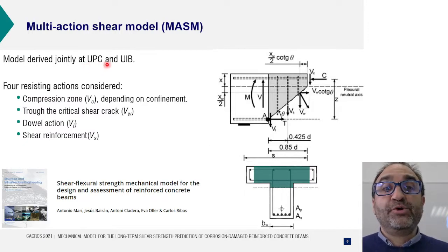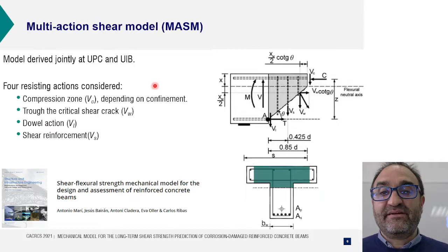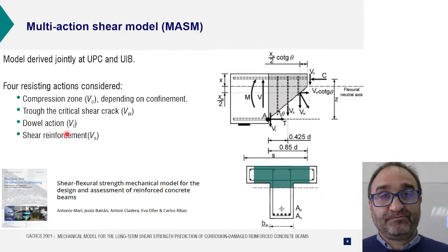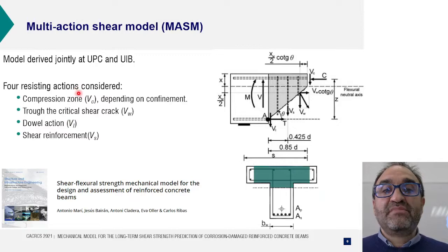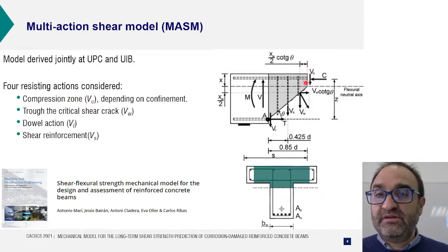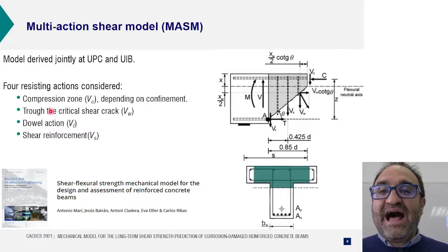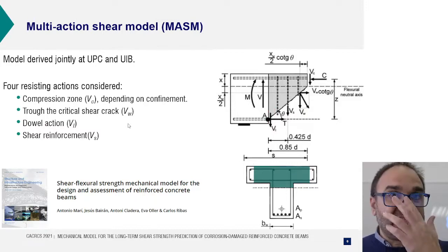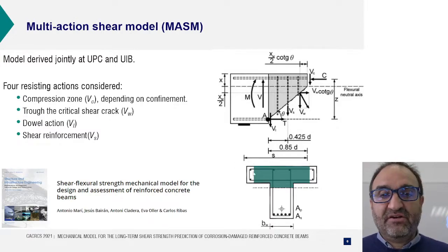Several years ago, at UPC and UIB, we developed the multi-action shear model, a mechanical model that considers the contribution of the stirrups, of the shear reinforcement, Vs, you can see it here, but also the concrete contribution through three different concrete actions: the shear transfer through the compression zone, here, the shear stress transfer through the critical shear crack, this component here, and of course the dowel action of the longitudinal reinforcement. This model was developed for rectangular beams, but was very soon extended to beams with T cross section.